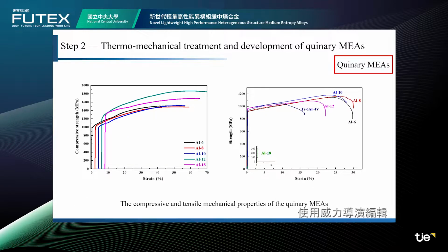In the compression testing, the plastic deformation of each alloy can exceed 50%, and the strength is enhanced with the increase of the aluminum content. However, in the tensile testing, the ductility of aluminum 12 is reduced significantly, while aluminum 18 is a completely brittle fracture.